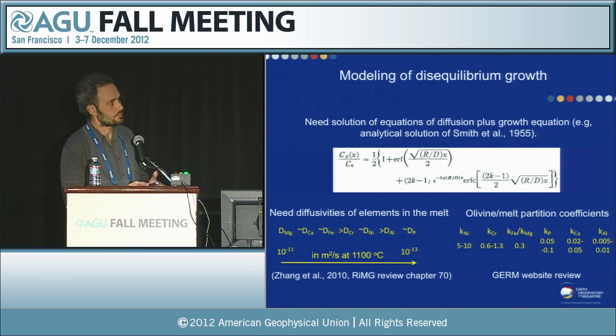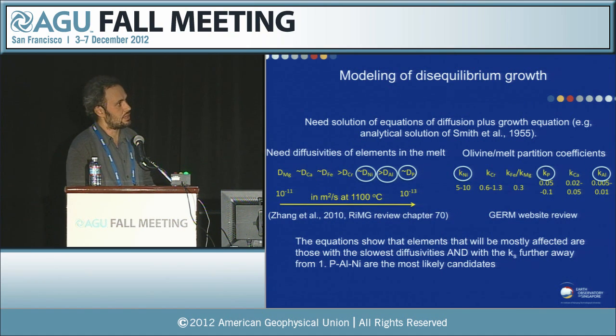And with this we can do something. We use a growth plus diffusion equation, and we can take the analytical solution of Smith et al., who has been around for quite some time. What we need to plug into this equation is the diffusivities of the elements in the melt, which gives some values here. Phosphorus is about as low as aluminum, relatively slow, and iron, calcium, magnesium are faster. We also need the partition coefficient: the lowest partition coefficient is aluminium, then calcium, phosphorus, and nickel is compatible. So these equations say that the elements with the slowest diffusivities and with KDs that are farther away from 1 will be the ones potentially showing more of this kinetic effect.